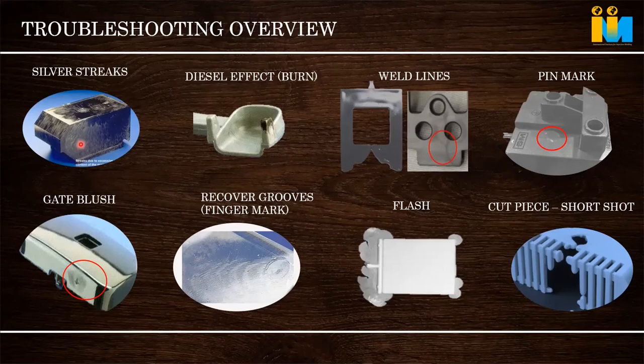For commodity plastic, simple plastic, this may not be a major issue, but if you are going with engineering plus specialty plastic, this is a very major issue. Nylon has this problem very severely, because nylon absorbs a lot of moisture. So nylon is known as a hygroscopic material. Hygroscopic means materials which absorb water highly. Whenever we are using a highly hygroscopic material, it has to be taken care of properly, pre-dried, and it is better to go with a dehumidifier sort of arrangement.